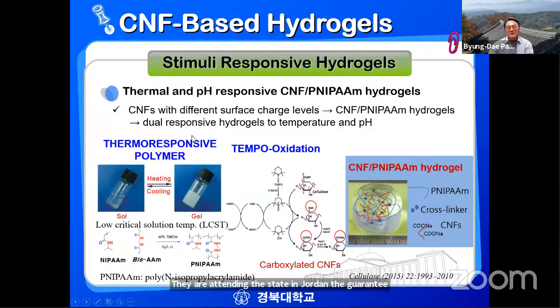So idea is we combine the thermal responsive polymer with TEMPO oxidized cellulose, this nano cellulose, which is CNF, with different surface charges using different oxidant levels, and then try to make the stimuli responsive hydrogel, which is responsive to temperature and also pH. That's the idea. You know, when you have this kind of hydrogel, you have hydrogels and polyNIPAM.